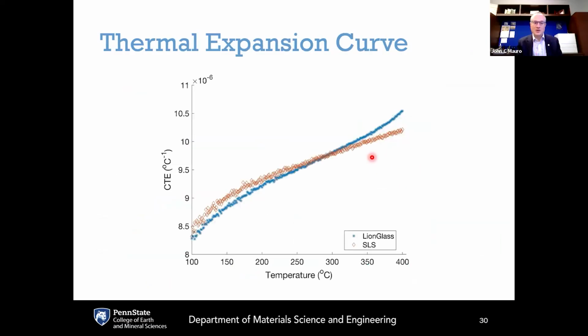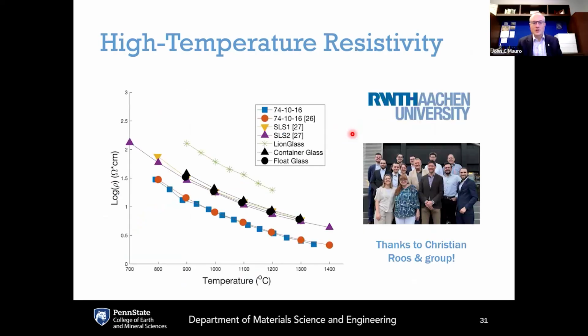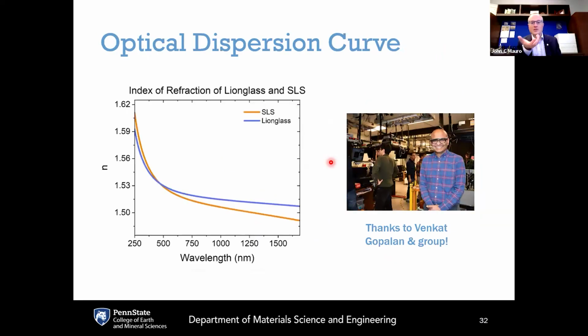What about thermal expansion coefficient? The CTE is actually very similar between Lion Glass and soda lime silicate, so there's no difference in terms of the thermal shock performance. Another big trend in glass manufacturing is the move away from fossil fuels and towards electrically resistive glass melters. Working with our collaborators here at Aachen University in Germany, we showed that the electrical resistivity, which needs to be in a certain range to enable glass melting, is also in a good space for electrical melting.